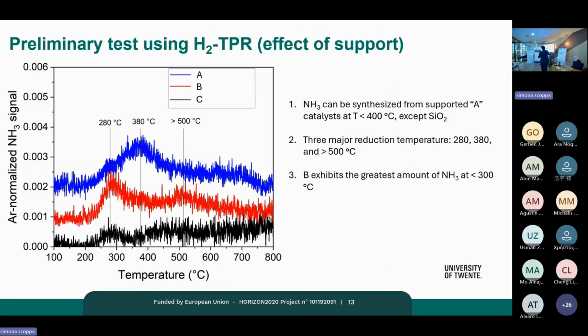Now, what you see here, I cannot tell you exactly what ABC are. I can just tell you that there are metal nitrides that contain a certain concentration of oxygen, which means that they will be scalable. We don't have to work in a glove box. We don't have to work in an inert environment for their manufacturing, which means that they will be much easier to scale up. And what you see here is a temperature programmed reduction. So this is the first step in the catalytic cycle. And what you see in this plot is the temperature against the normalized intensity of the ammonia peak. And this is in the absence of any metal function. It's just a metal nitride, metal oxonitride.